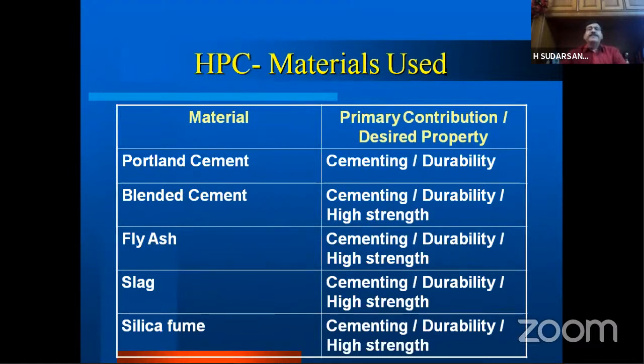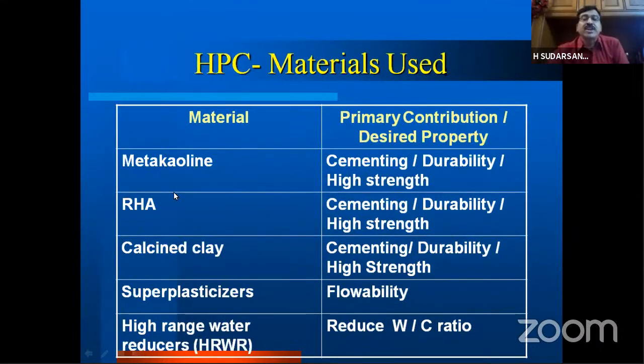The different types of materials we use in high performance concrete and their primary contributions, I just listed them out. You can have a quick look at them. Portland cement, the blended cement. In fact, blended cement is much better than ordinary Portland cement. Blended cements contribute to durability as well as high strength. For blending, we use many types of mineral admixtures like fly ash, slag, and silica fume, metakaolin, rice husk ash, calcined clay. These are all mineral admixtures. They improve the durability and reduce the permeability.